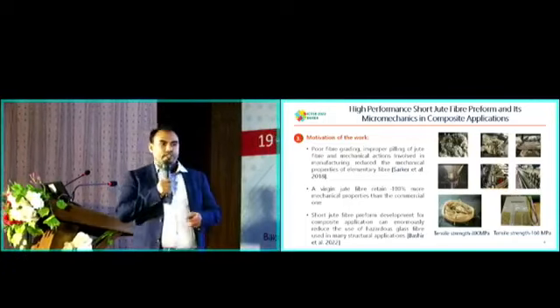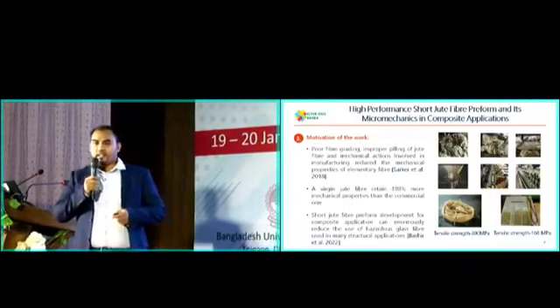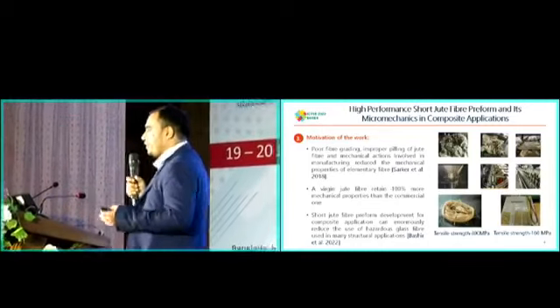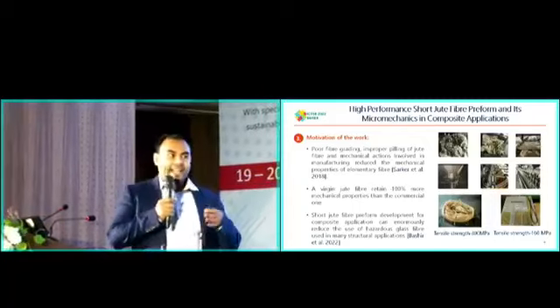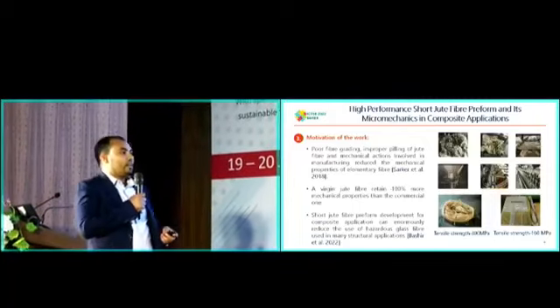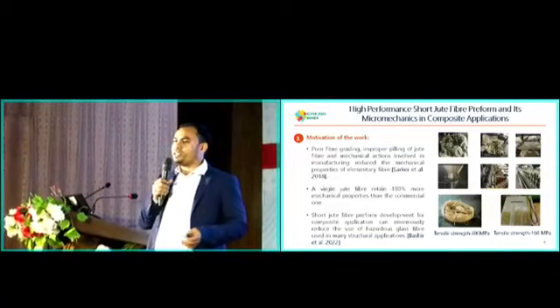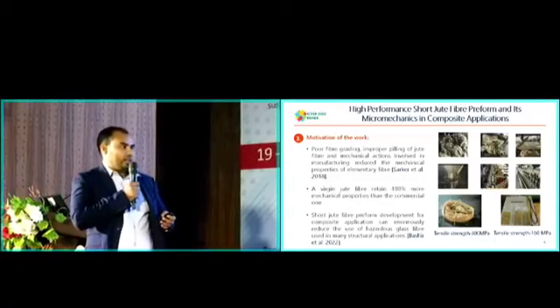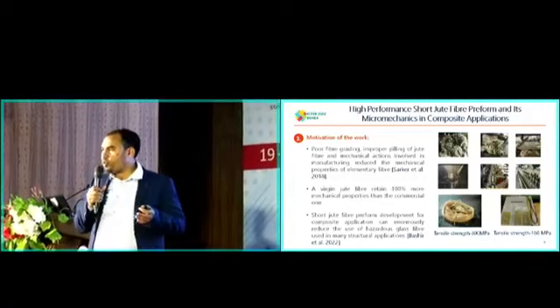Before the project started, we were trying to search for the motivation of the work, like what is happening with natural fibers around the country, the existing materials, and what physical and mechanical properties exist in the materials. We found that the tensile strength, which is very important for selecting this material in composite applications, suffers from very poor mechanical properties. The tensile strength is only 160 megapascal, and the stiffness is 8 to 10 gigapascal when it is received from the industry.